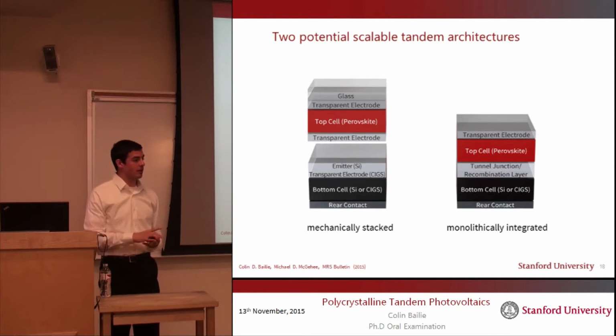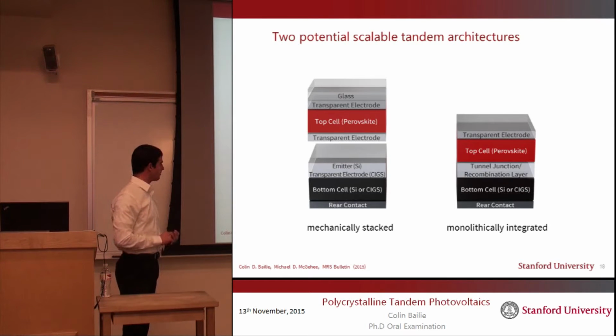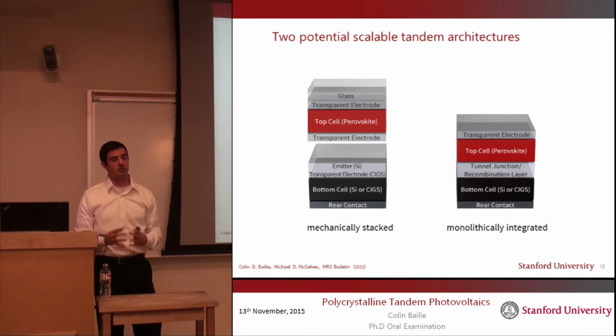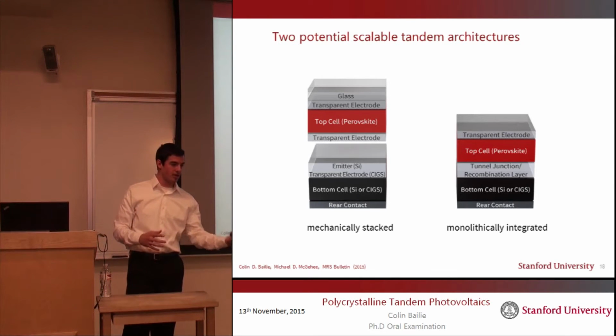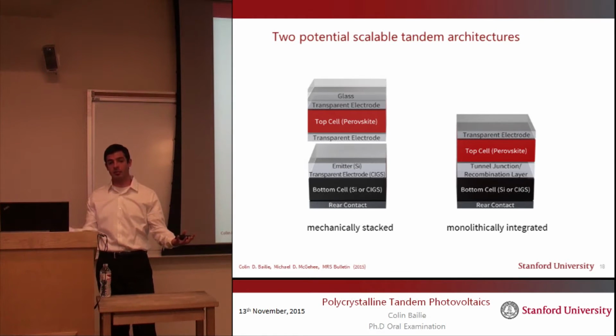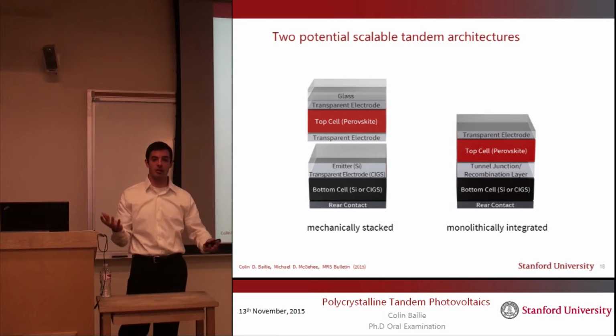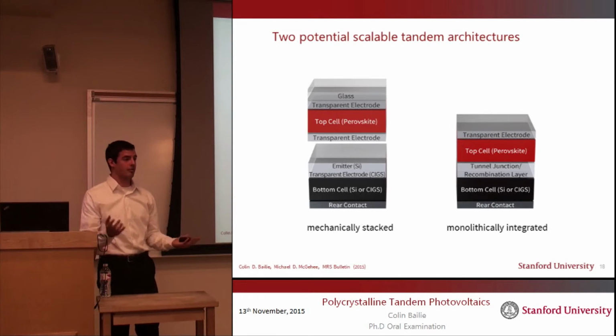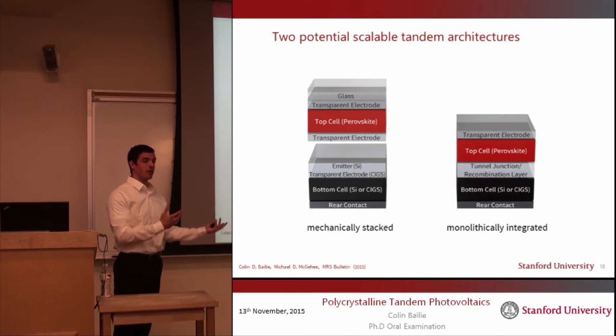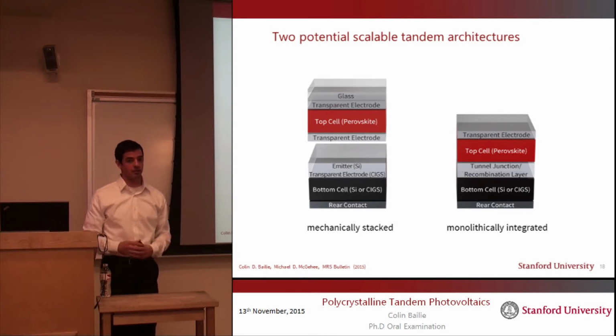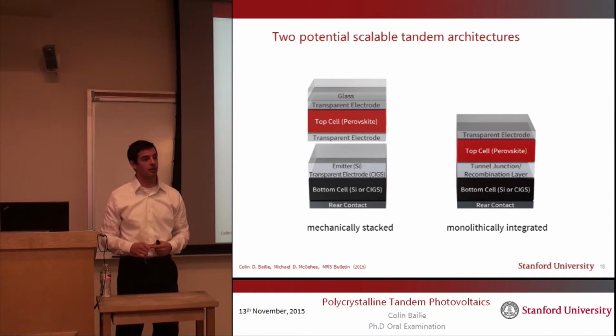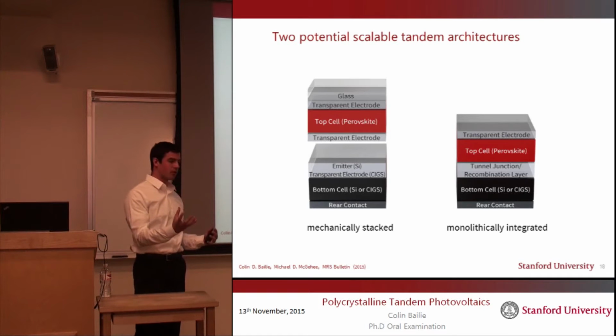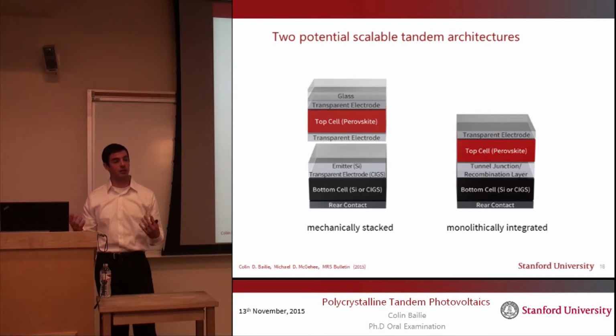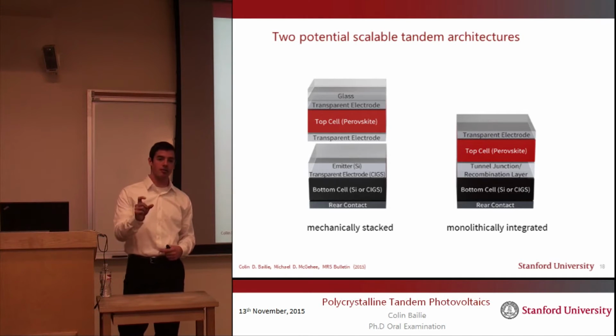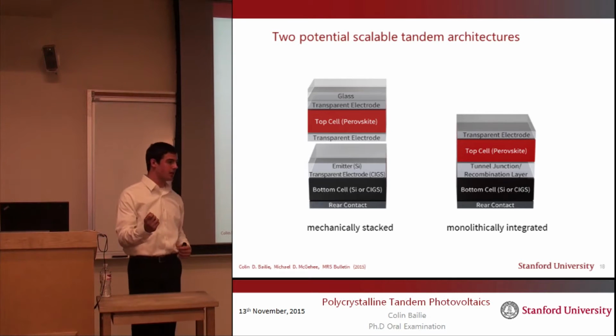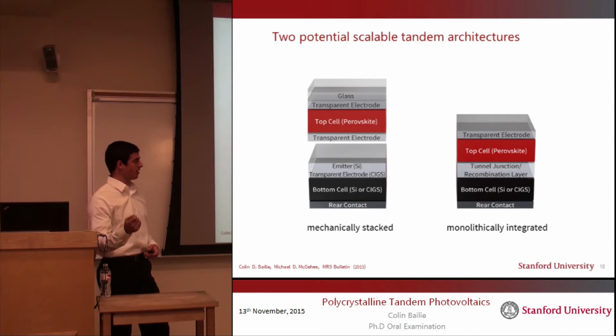To go about then making a tandem, now that we've decided on the materials that we're going to use, we have a couple of different options. We can either go the mechanically stacked route, where we make separately a silicon solar cell from start to finish, and we make a perovskite solar cell from start to finish. And then when time comes to make the tandem, we simply put them on top of each other, and that's the end of the story. The other option is a monolithically integrated tandem, which is the more classical design, and that's what the solar cell on the end of the gloved finger was made using, where you start with a silicon wafer and you engineer in either a tunnel junction or a recombination layer, and you deposit the perovskite directly on top, such that at the end of the day you're holding a single solar cell that has multiple junctions inside of it.